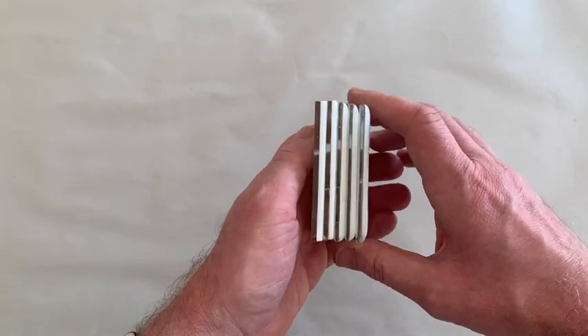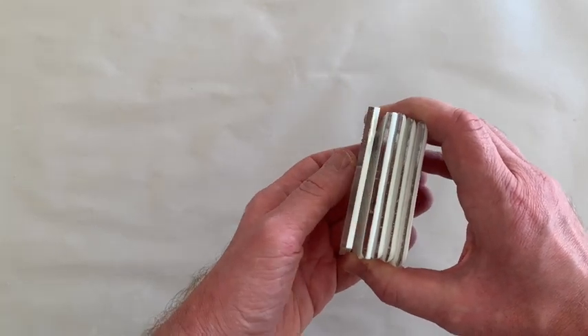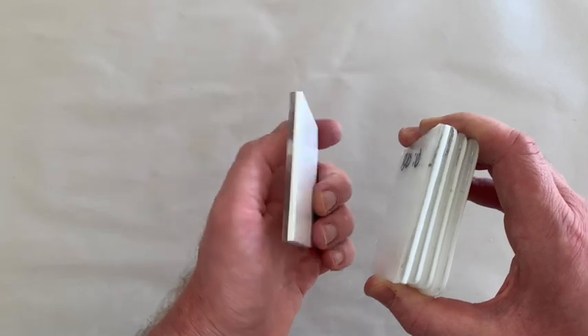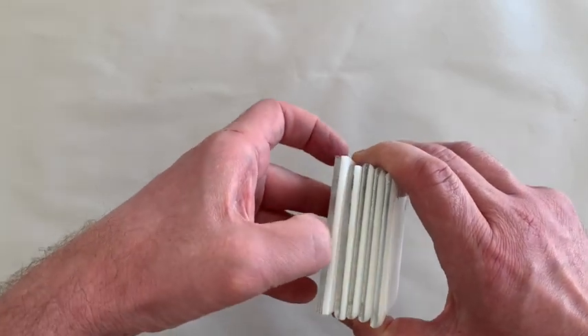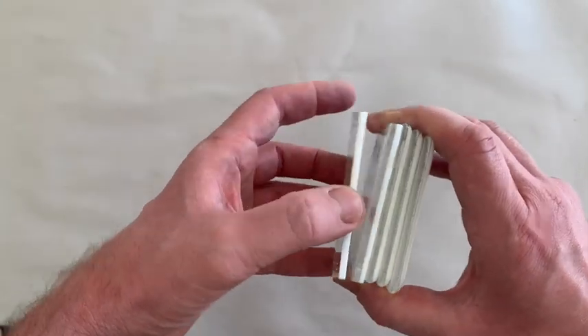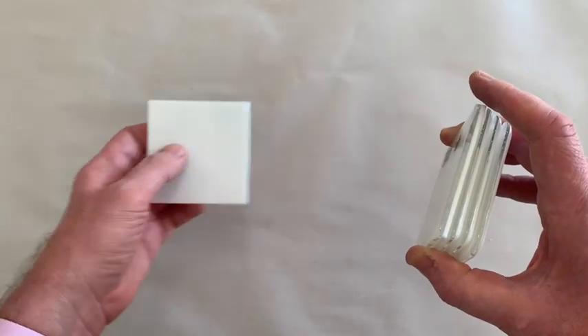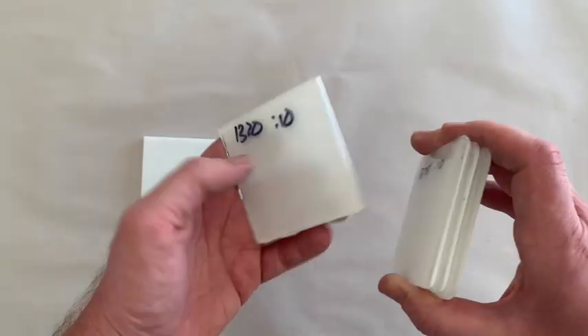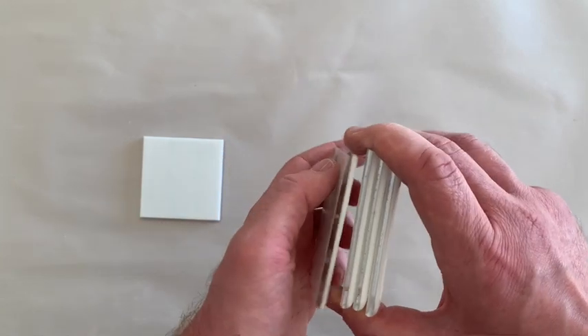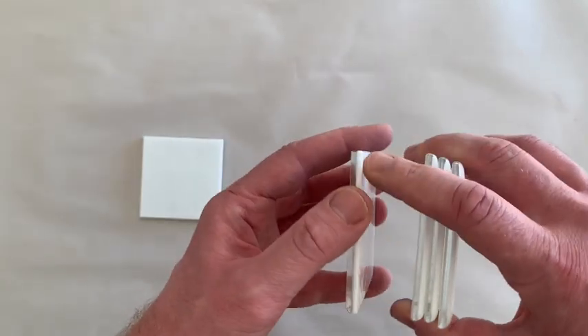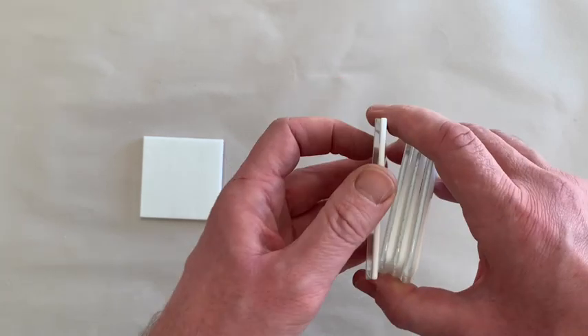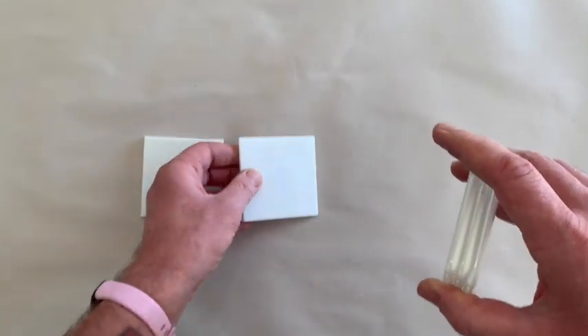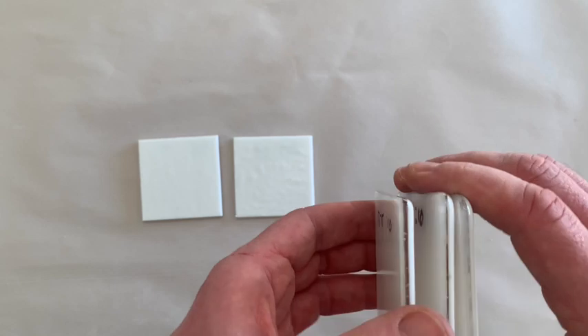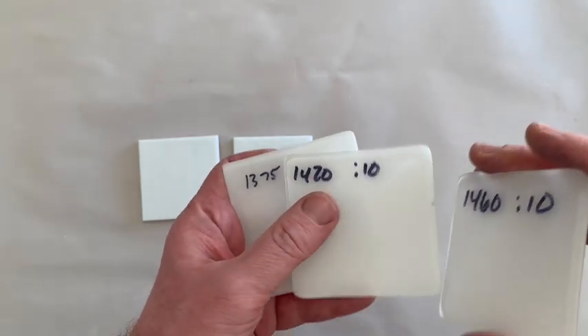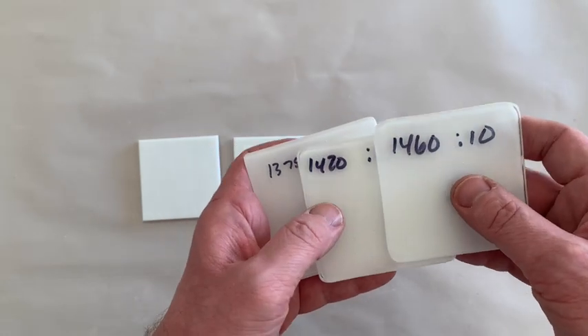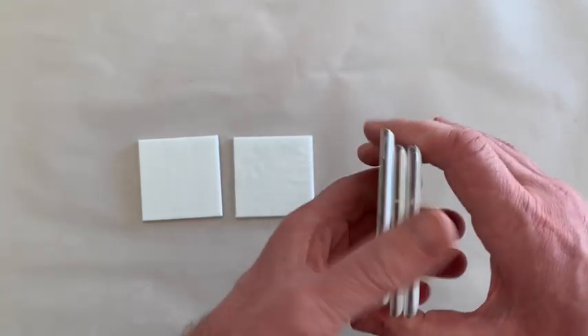From the samples made only with two layers of sheet glass, you could see that at 1265 degrees, the corners of the glass still appear separated, even though they are tacked together. The separation remains on the sample fired at 1320 degrees as well, though it is less pronounced. Beginning at 1375 degrees and up to a full fuse at 1460 degrees, the two sheets of glass are fully combined with a rounded bullnose profile.